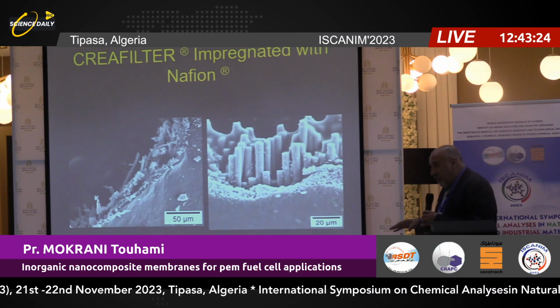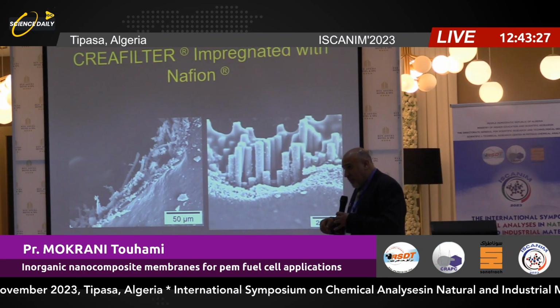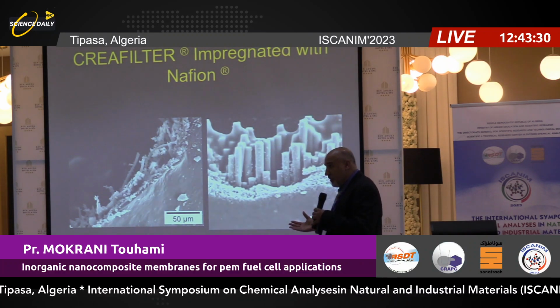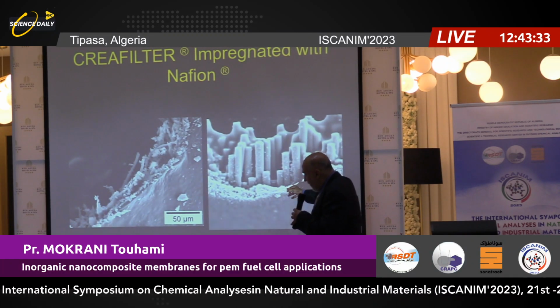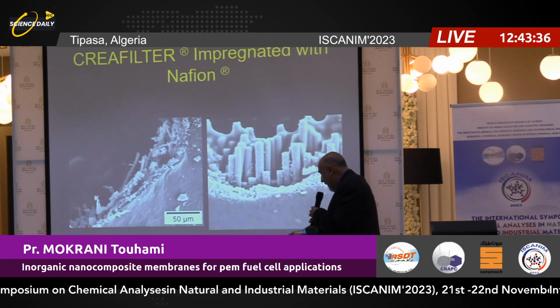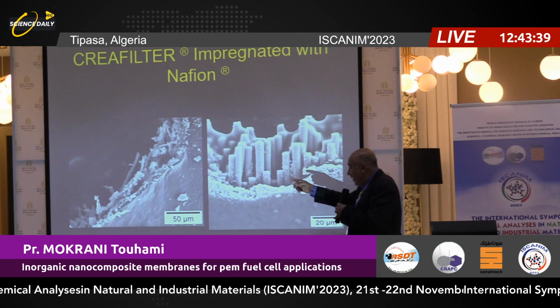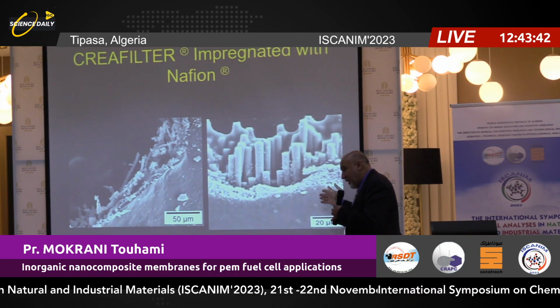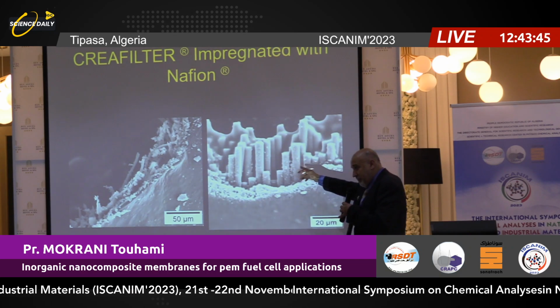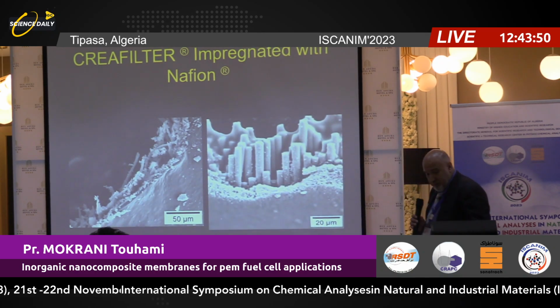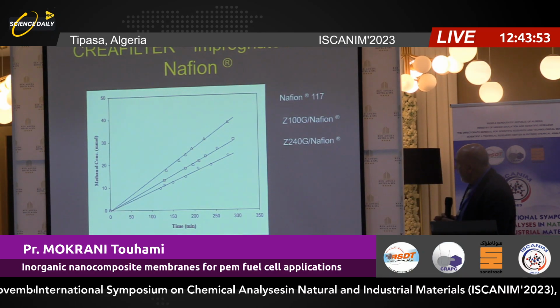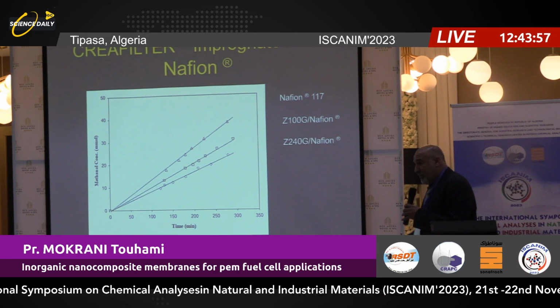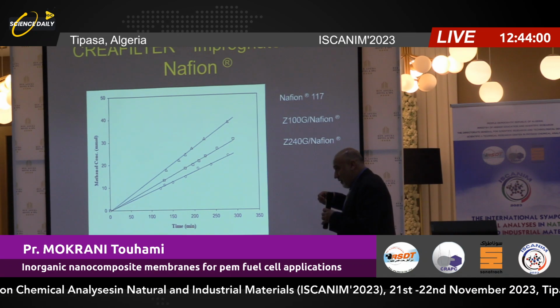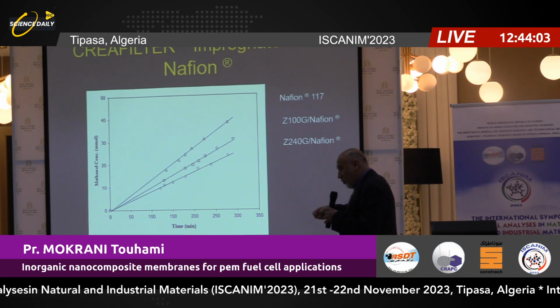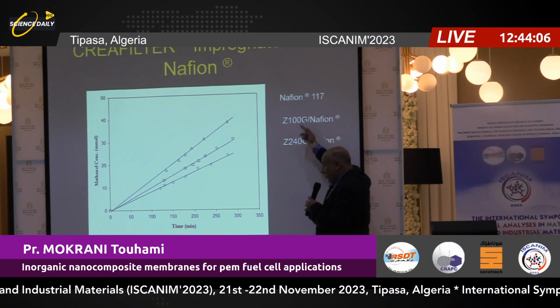So the second type of membrane, we take the flexible ceramic material and we impregnate it with Nafion solution. So you can see here this one Z100G and this one is 240 Nafion. This one is better than the other one because the loading of Nafion is much higher. And I assume it's because of the pores, because I think this number is the pore size. So if we see the permeability in this case, the ceramic Nafion solution, it's much better than the reference for methanol permeability.